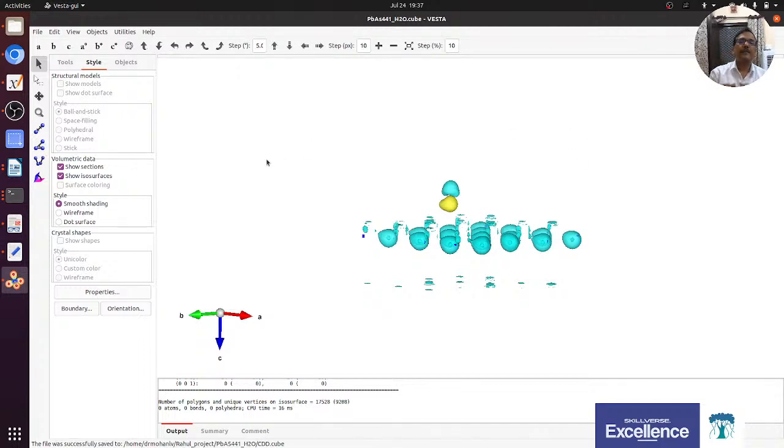So the method is simply: when we have to create that planar structure, especially for such type of project, we have to optimize that. Then we have to create that molecules, and then optimize. Then we will link this by using this VESTA GUI, and after some practice you can put it at a particular position you want, and then fix that planar structure, and release the molecules, and let it be optimized.